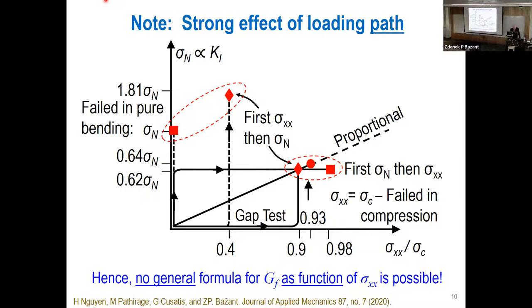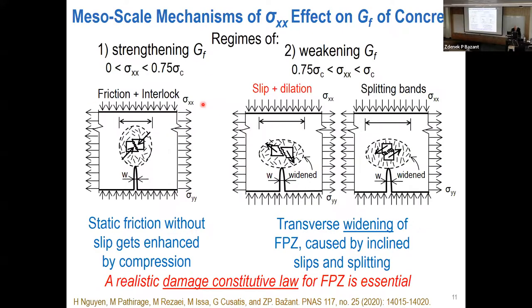So I plot here effective K1, or energy release rate, at the crack tip versus the axial stress. And the data encircled by red should come to the same point for different paths shown here. So this is a significant difference here. Even bigger here, these two data should be the same if there was no path dependence. So how can we model it with a formula? That's not generally possible. So we need a direct description.